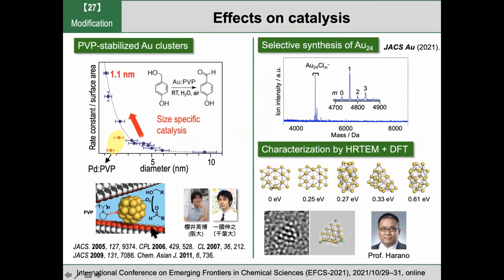Our previous study shows that small gold clusters act as highly active catalysts for oxidation reactions. Although gold is chemically very inert, when you reduce the size of the clusters down to 1 nanometer, they act as catalysts for oxidation reactions. Recently, we can control the size of the clusters with atomic resolution. Now we can synthesize Au24 clusters, and we are studying the structures by using high resolution TEM images and theoretical calculations. We found that the structures are very flexible, so they are not rigid metal, but very fluxional.